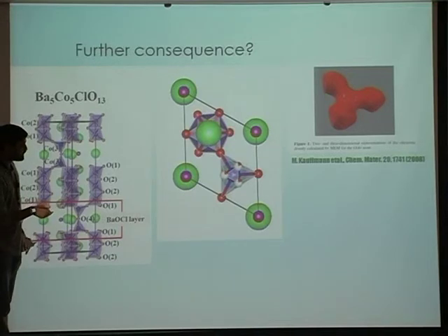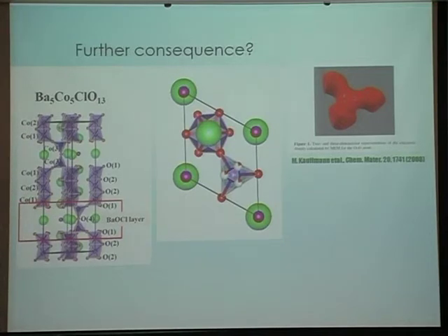What the diffraction told us is that unfortunately this particular oxygen does not really sit here where it is expected to sit. Instead, it finds 3 possible symmetric positions around the mean position and has a shared stay. 1/3 stays here, 1/3 here, 1/3 here. XRD, or diffraction, being an average probe, that's the way it's defined. Even certain calculations showed exactly the similar charge density for this particular oxygen.